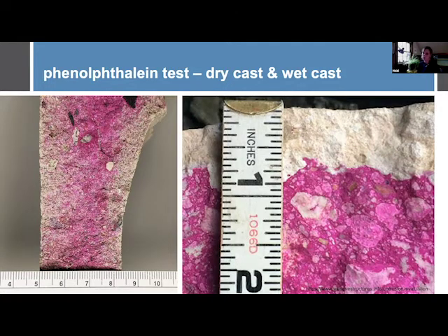Until recently, the concrete masonry industry assumed that the CMU would carbonate the same way. However, recent testing we've done has shown otherwise. The block on the left is about 2 months old. And as you can see, the carbonation is occurring into the concrete and not just at the surface, and at a much more rapid pace.